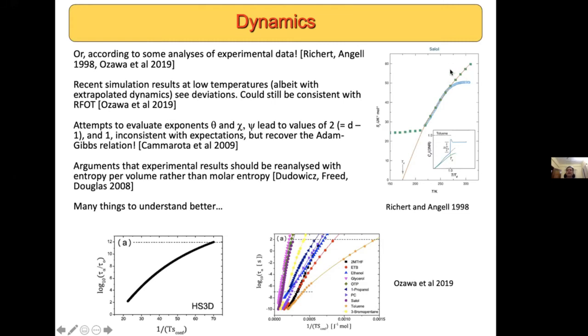But at higher temperatures, it doesn't, and it's not indicated on this diagram. But where you begin to fall away, when the two data sets begin to disagree, is around what is called TB in this literature, which is identified with the mode coupling crossover. So even experiments seem to suggest that at higher temperatures it shouldn't be valid. But in simulations you see that it's valid in those temperatures.